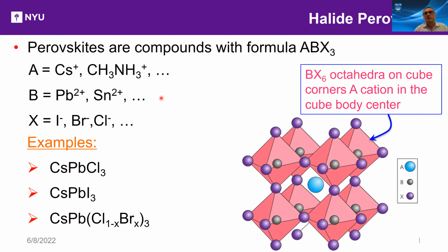They're compounds with formula ABX3, where A is a monovalent ion, B is a divalent ion, and X is a halide. And it's typically cubic, although the definition is relaxed. For perovskites, you can have orthorhombic and rhombohedral structures and other structures. But the characteristic structure is this BX6 octahedra. It is an octahedra of a metal and the halides, and they reside at the corners of a cube with the A ion in the center.